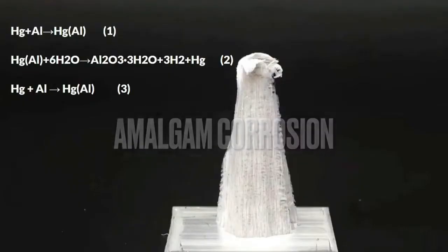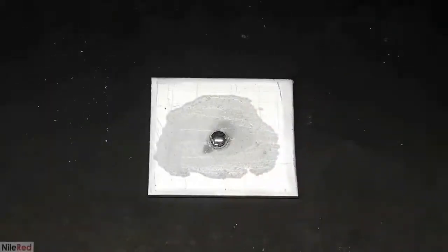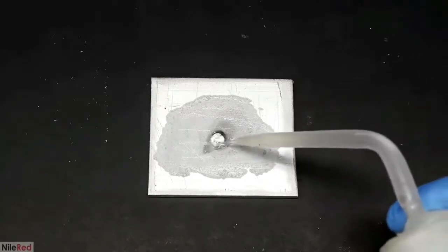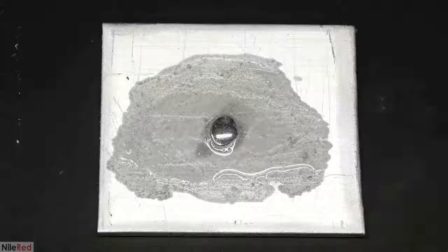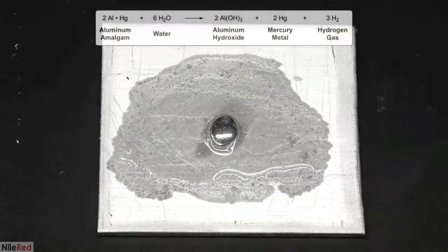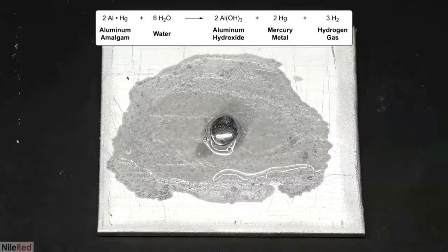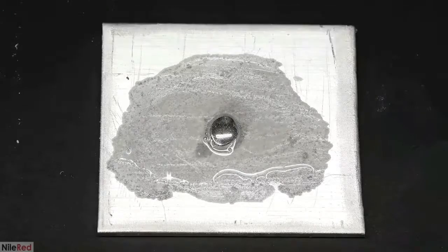Then we move on to the second mechanism, amalgam corrosion. The second mechanism of aluminium degradation is amalgam corrosion. Amalgam corrosion is the combined reaction of mercury and moisture on aluminium. It's similar to amalgamation, but the difference is the presence of water. Through the equation, we can notice that the aluminium amalgam will react with the water to form aluminium hydroxide, hydrogen, and mercury. The presence of bubbles indicates the presence of hydrogen, and the mercury product will react again with the aluminium to form the aluminium amalgam.